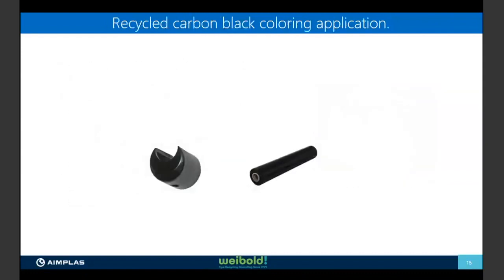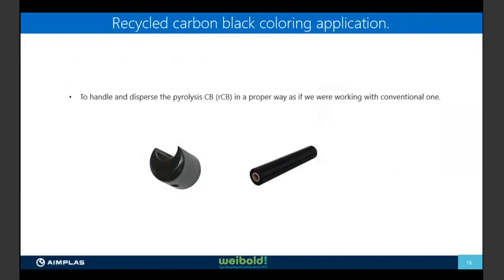To do that, what we suggest is to check how it works in some thick parts. You know that when we have injection molding, we can have thick parts with probably 2, 3, or even 4 millimeters, okay? But at the same time, we want to check if this tinting capacity is the same in very thin items, like a film, which can have a much stronger influence on dispersion, because you know that if you have something of a few microns, dispersion will be much more important to achieve, unlike thicker parts that we have in injection. So what we try to do is disperse this recycled carbon black in order to not modify the normal processing of people that were dispersing the conventional one. But there has been a mistake in the animation, sorry.